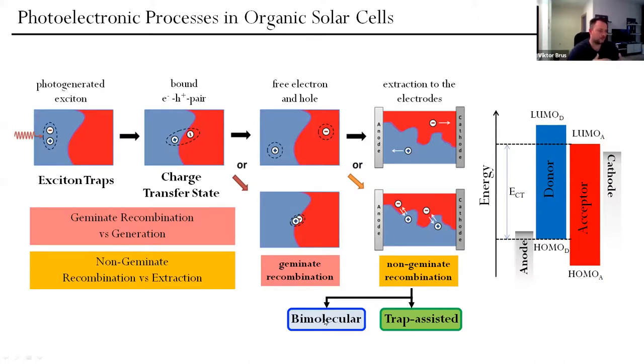So bimolecular recombination in most cases should be radiative. As a result, a photon should be emitted back. However, if you dig deeper into this, there are possibilities of non-radiative bimolecular recombination as well. And there is another type of non-geminate recombination loss, which is trap-assisted. Trap-assisted recombination can be in the bulk of the active layer or at the interface between active layer and electrodes. That happens via some defects and impurities in the active layer, which form deep energy levels in the band gap. And those serve as efficient recombination centers, which follow the Shockley-Read-Hall recombination statistics, with defect levels in semiconductors within the band gap. In that case, we can eliminate these losses by making high purity active layers and high quality interfaces with surface passivation.